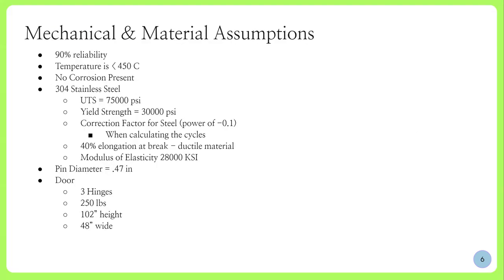And then for our mechanical and material assumptions that we used to determine our fatigue factor of safeties, we used 90% reliability. The temperature is below 450 degrees Celsius. No corrosion is present because that would greatly complicate the analysis and add in stuff that we have not learned yet. Our material is 304 stainless steel with an ultimate tensile strength of 75,000 psi, a yield strength of 30,000 psi, and a steel correction factor of negative 0.1 for calculating the cycle to break. 40% elongation at break means it's a ductile material. Our modulus of elasticity is 28,000 ksi.